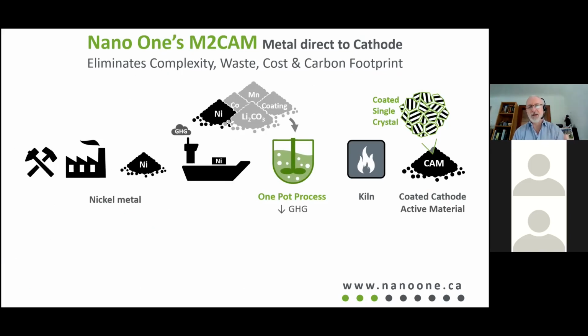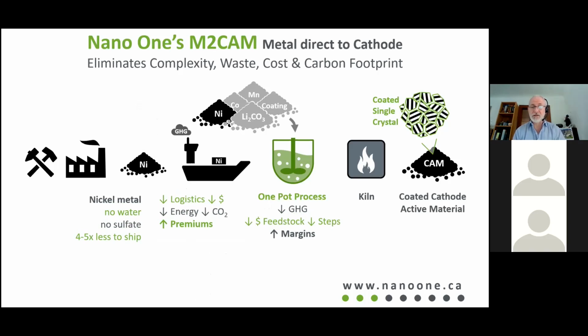You add the nickel, cobalt, manganese metal with all the coating and doping materials and the lithium carbonate, because we don't have to convert to lithium hydroxide. We can actually use either, but we prefer carbonate because it's easier to handle. In our one pot process, we dump the extra shipping costs. We have no water in the metal. There's no sulfate in the metal. And there's less to ship. With cheaper logistics, energy costs go down, CO2 goes down, and premiums for the miners go up, so they're much happier about it. The one-pot process has lower greenhouse gas emissions, lower cost of feedstocks, fewer steps in the process, no waste and much less water.